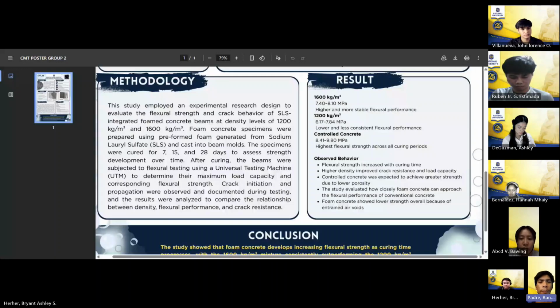After curing, the beams were subjected to flexural testing using a universal testing machine, or UTM, to determine their maximum load capacity and corresponding flexural strength. Crack initiation and propagation were observed and documented during testing, and the results were analyzed to compare the relationship between density, flexural performance, and crack resistance. So for the next reporter, for discussing the results, may I call on Mr. Herrera?